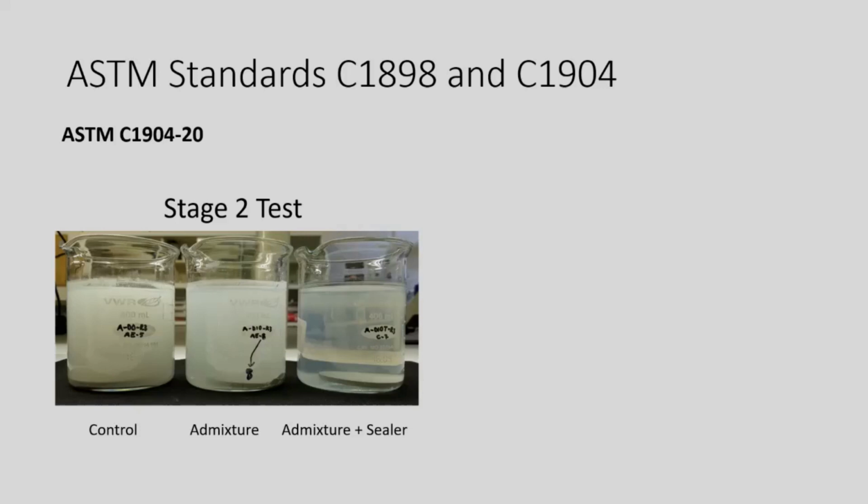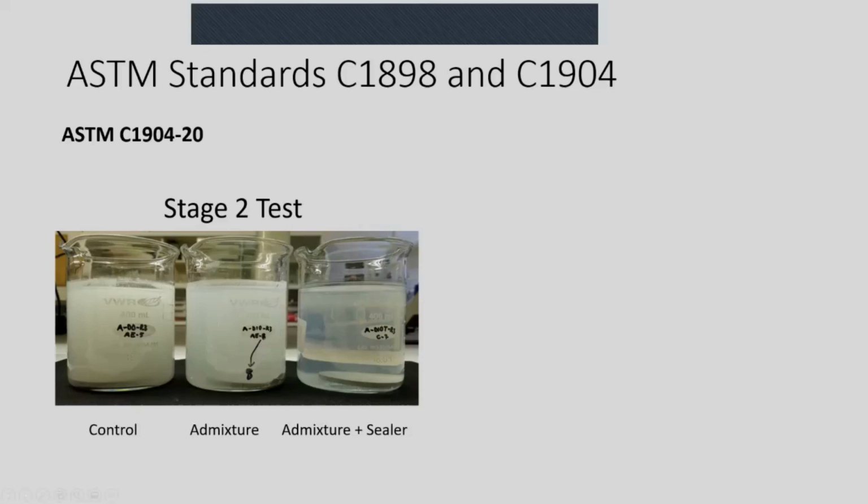And the picture you see here on the left is a high amount of bacterial activity in that solution. It has no treatments at all. In the middle, you see a treatment with an antimicrobial inside of the matrix of the mortar disc. And on the right, you see a picture of a mortar disc with the antimicrobial in the mortar disc and on the mortar disc. And it's important to note that you see a very cloudy picture to the left, somewhat cloudy in the middle, but on the right, the picture is pretty clear still with no microbial activity in that broth.